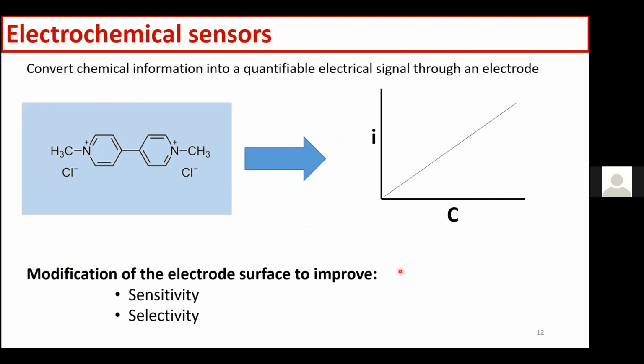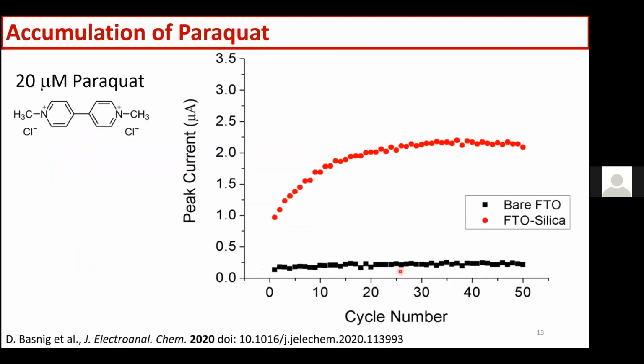And so the idea was how can we use this silica to improve the sensitivity and the selectivity to make electrochemical sensors. So we looked at the effect of cycling paraquat. We did a series of 50 cycles at a modified electrode and a bare electrode, and you can see that at the modified electrode the signal is increasing before it reaches a plateau. So meaning that with time and with the number of cycles we are accumulating the probes inside the film.